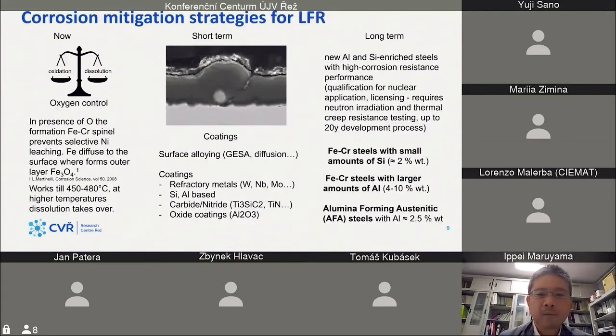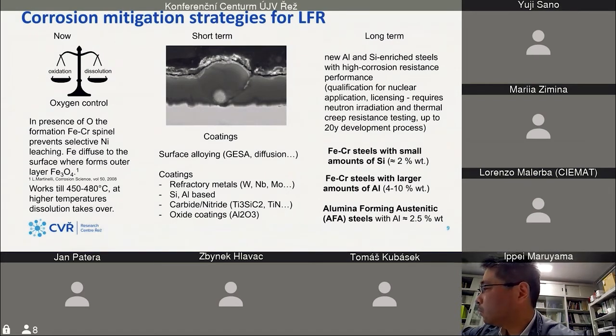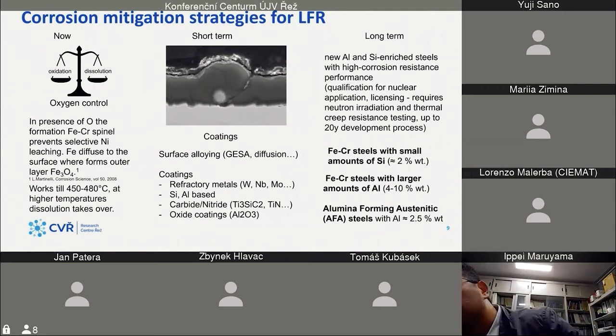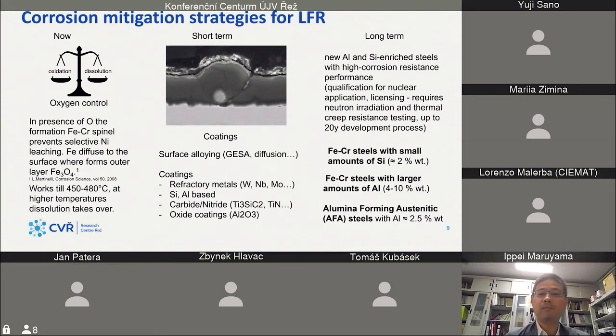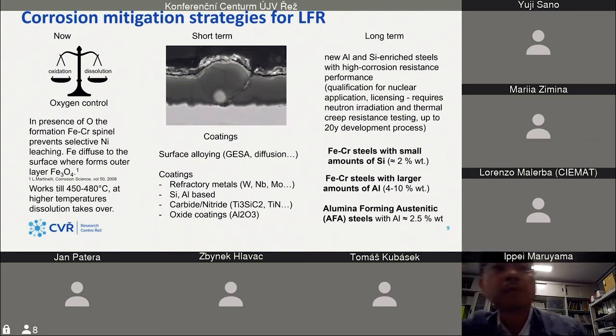So, mitigation strategies for LFR. Right now, oxygen control is available. It's a kind of balance between high-temperature oxidation and dissolution. In the presence of oxygen, we can grow some Fe-Cr spinel that prevents nickel leaching out. This strategy works up to 480 degrees C, but at higher temperatures the dissolution takes over and we can see some localized attacks.